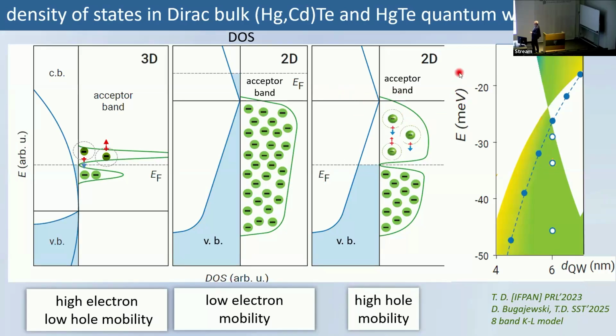By contrast, if you go with Fermi energy to this hole portion of Dirac cone, you end up with a situation where you have a resonance state, and again you expect high mobility. So in the case of electrons, we have high electron mobility in 3D and low hole mobility, but in 2D we have the opposite situation. We have low electron mobility but high hole mobility.